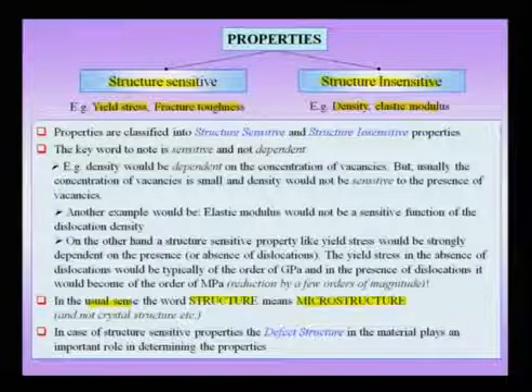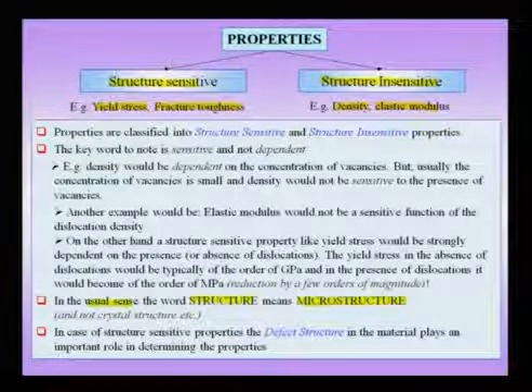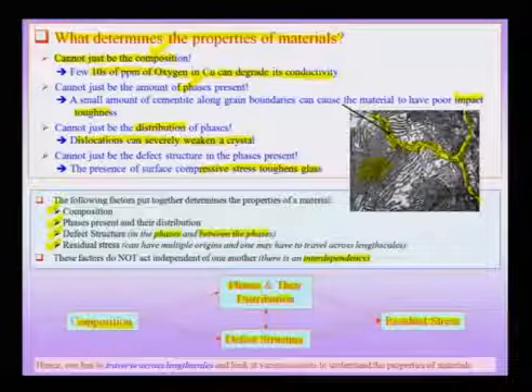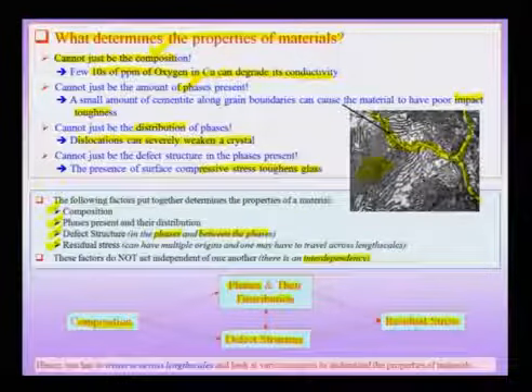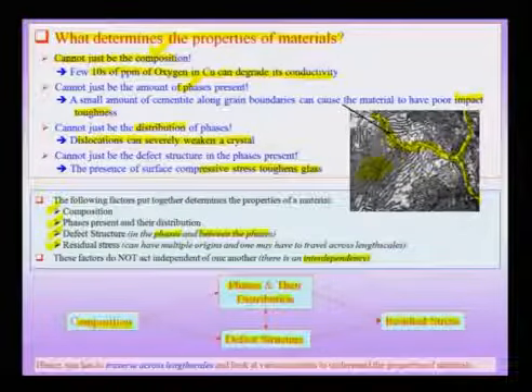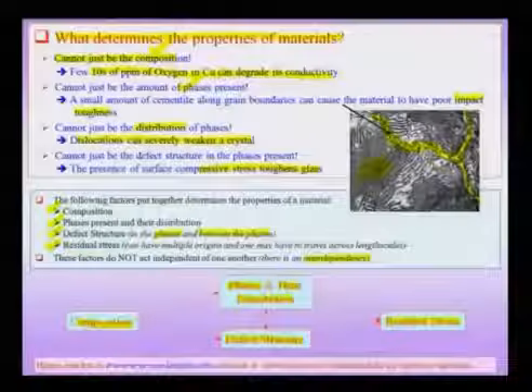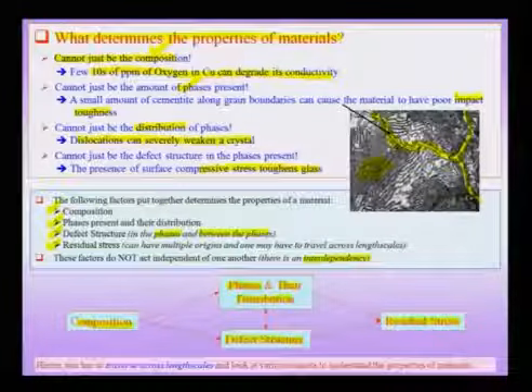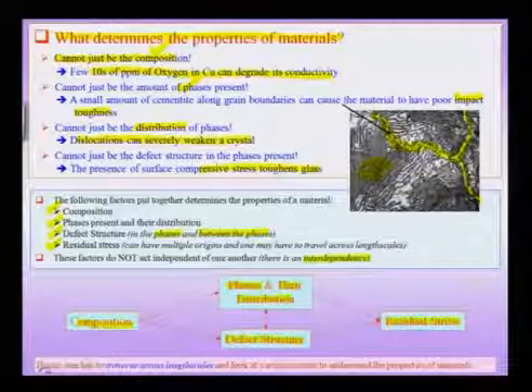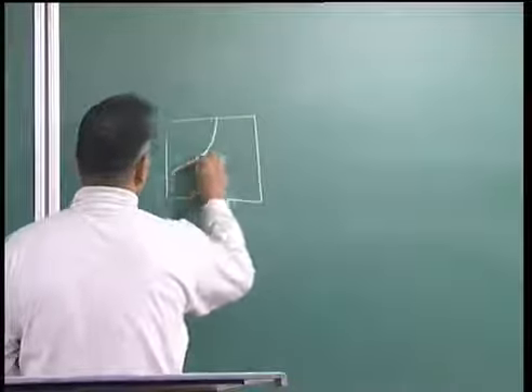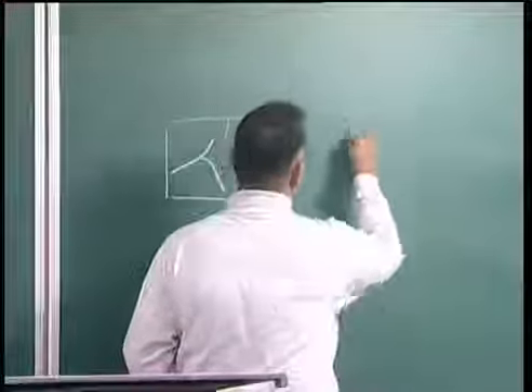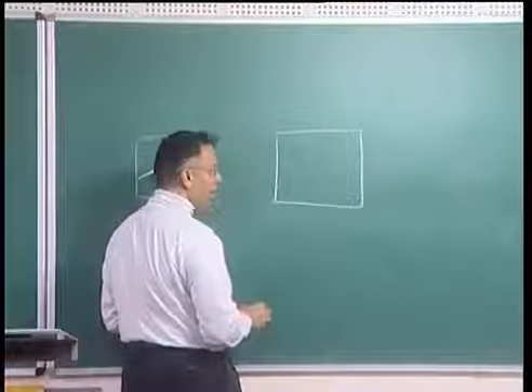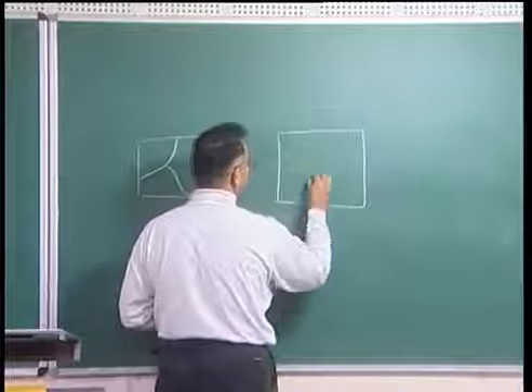Now, this classification is very, very important, because in the previous slide we had seen that the impact toughness of a material having cementite along the grain boundaries is very poor. Typically this is because impact toughness is a microstructure sensitive property. Suppose I was talking about density, then whether this phase is present along the grain boundary or as globules within the material, which I can draw schematically on the board now. Case 1 is the presence of cementite as a continuous network along the grain boundaries. In the second case, I can think of the same cementite in the same volume fraction present as small globules in the material.